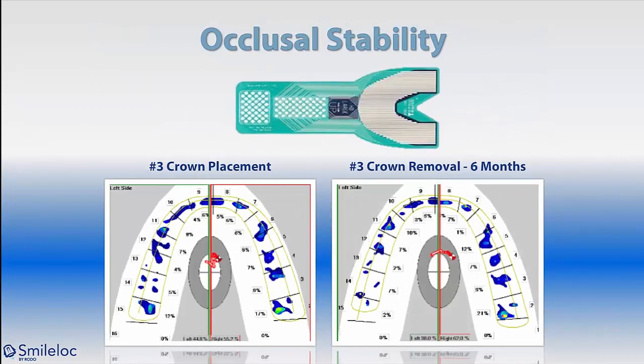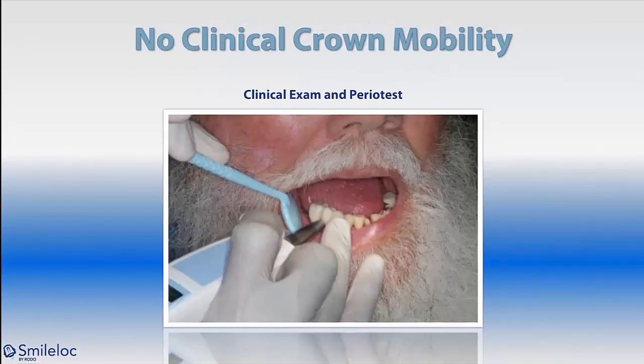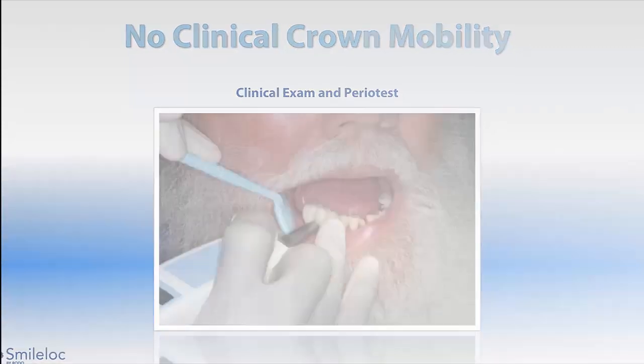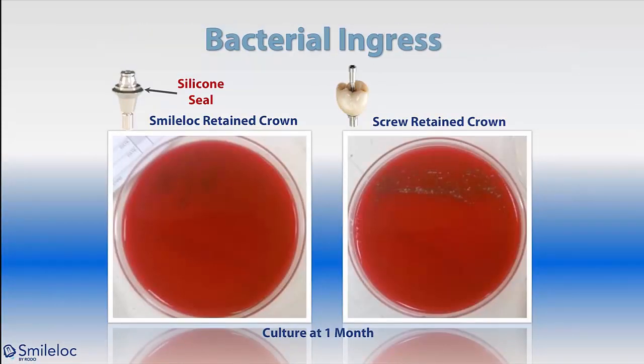They checked the occlusion with the T-scan, version 3, and you could see on the crown placement on tooth number 3 at 6 months, there was the same amount of occlusal contacts. Clinically, they went in to check for mobility, and they did a perio test. Mobilities were all normal. After removing the crowns, they did a Petri dish test to see if there was any bacterial contamination on any of the systems.